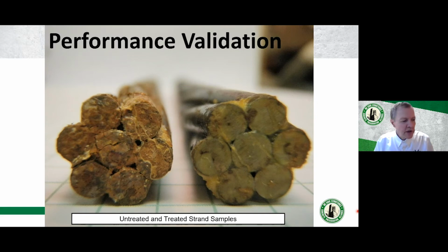The next few slides here I just wanted to show you are to give you some idea of, you know, is there a benefit in doing this in terms of corrosion protection as opposed to just pumping something into the strand. So the slide you see here is a very, very simple test. It's actually 2 pieces of strand, one of which was dipped into the impregnation material, the other one here was not, and then both strands were exposed to salt spray, and visually you can see there's a big difference in the amount of corrosion that's occurred.